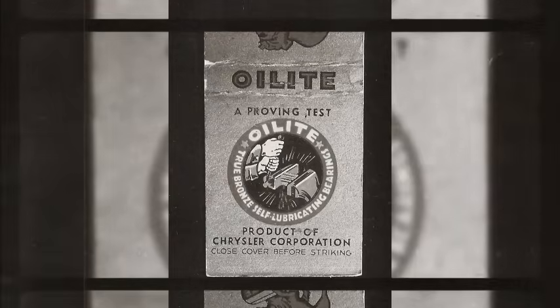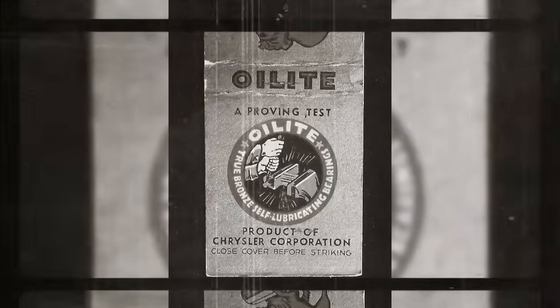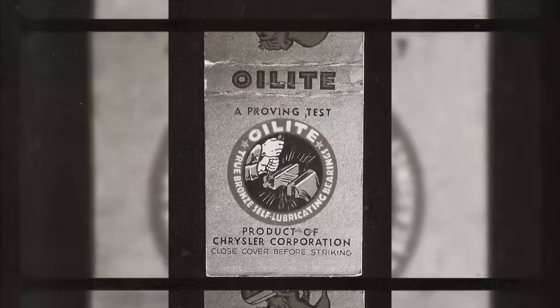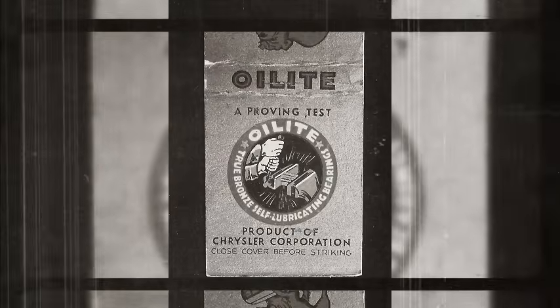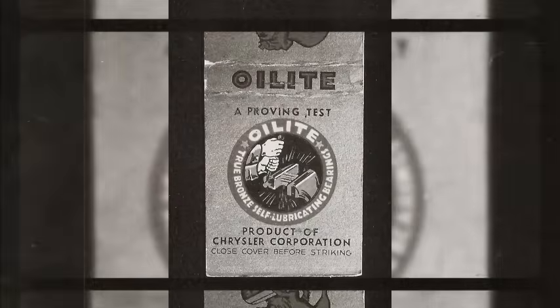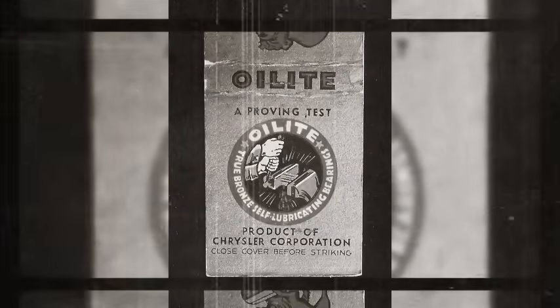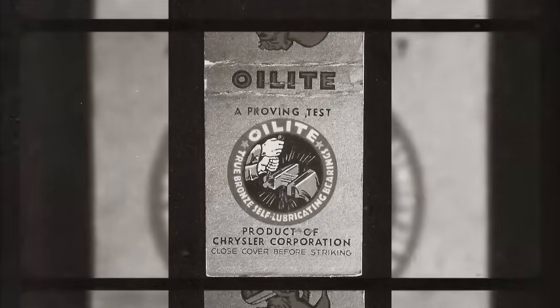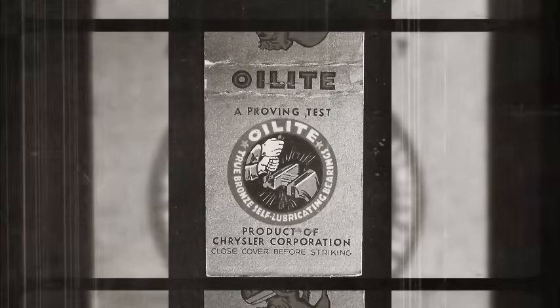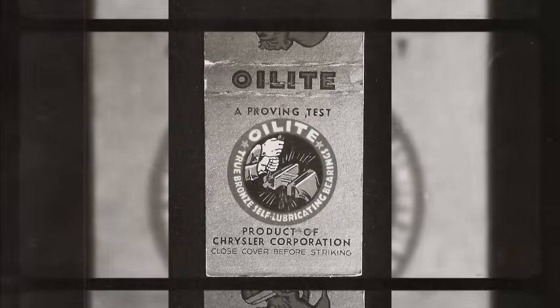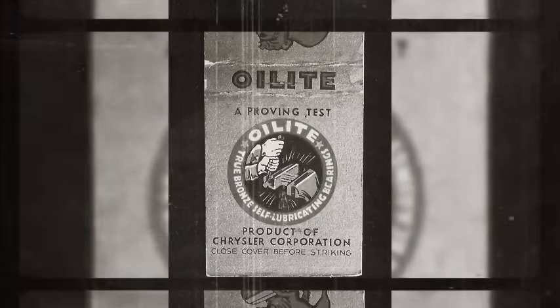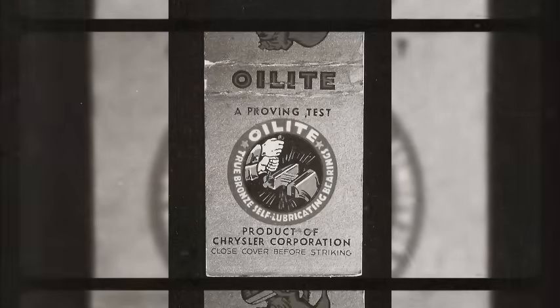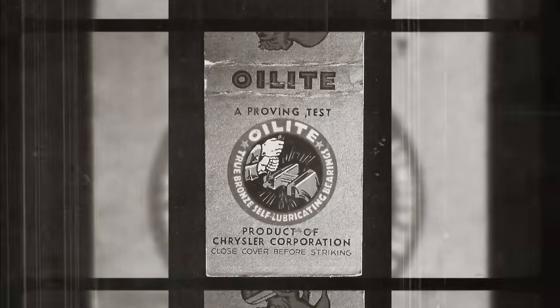Manufacturing process: 1. Powder preparation. Metal powders ground to precise particle size, typically 150 to 200 mesh. 2. Blending. Copper, tin, and any additives thoroughly mixed for uniform composition. 3. Pressing. Powder pressed in steel dies under 20 to 50 tons per square inch, forming green compacts. 4. Sintering. Heated in controlled atmosphere furnaces, oxygen-free to prevent oxidation, to 780 to 850 degrees Celsius, 1436 to 1562 degrees Fahrenheit, below copper's melting point, 1085 degrees Celsius, but hot enough for atomic diffusion to bond particles.